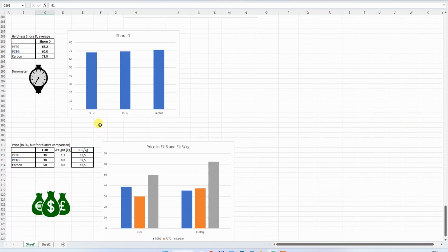So the lowest temperature was the PETG, which started to deform at approximately 61 degrees Celsius, and PCTG and PCTG carbon were very similar, approximately 75 degrees Celsius. And well, you saw the hardness test. Actually, yes, the PCTG is harder than PETG, but the carbon, probably thanks to those carbon fibers, resists penetration even better. So in this test, it was the hardest.